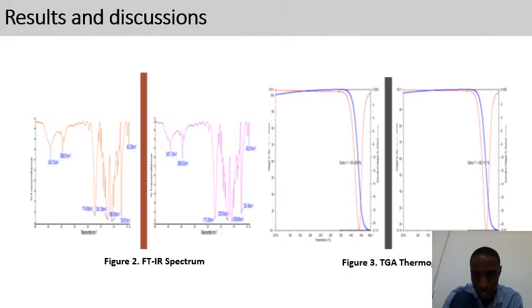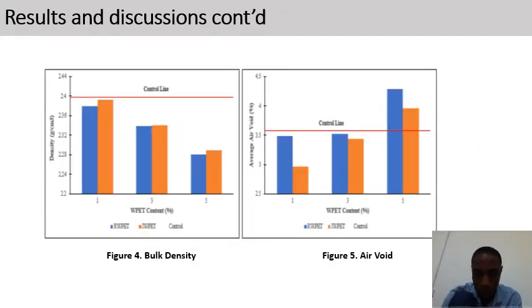There is an increase in the degree of decomposition and initiation decomposition temperature of the PET after irradiation, which validates the effect of cross-linking after exposure to gamma irradiation, and which makes this plastic more thermally stable when irradiated.